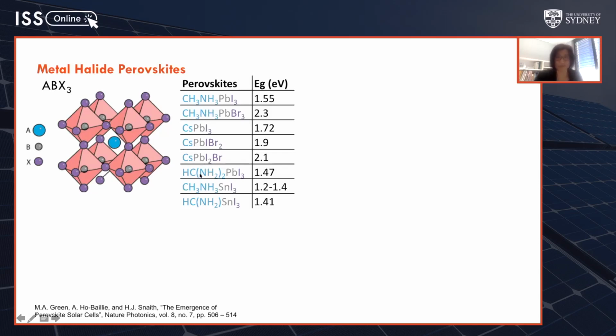The B site can be taken up by metal, which can be lead or tin, and then the X site is taken up by halide, which can be chlorine, bromine, or iodine. You can even mix them. It's got a very good optical absorption coefficient, and therefore it can be made in thin film form. Also, you can see that by just changing the composition, you can change the band gap. So why is it so good for tandem solar cells? You can actually stack a perovskite cell on top of another perovskite cell.